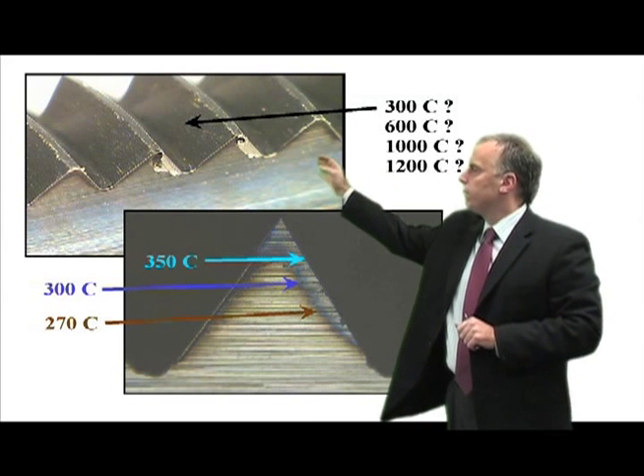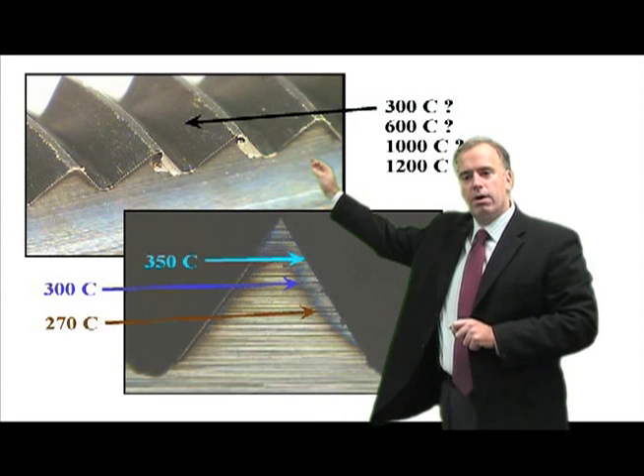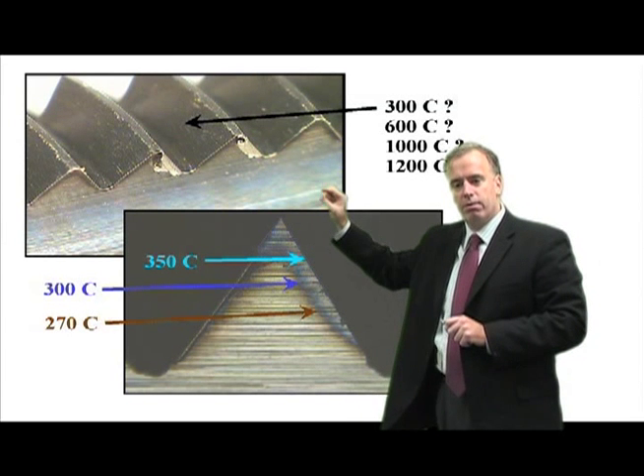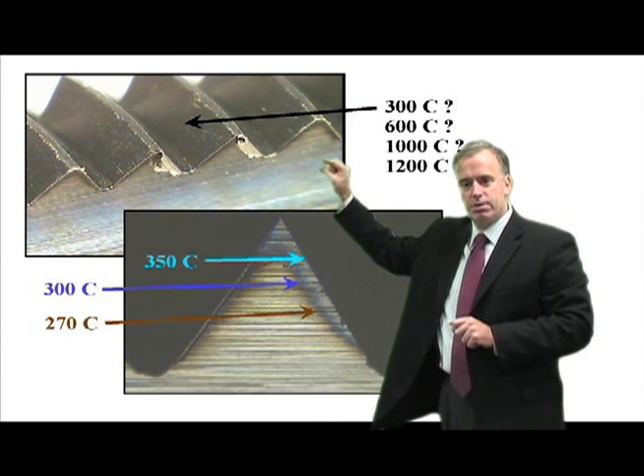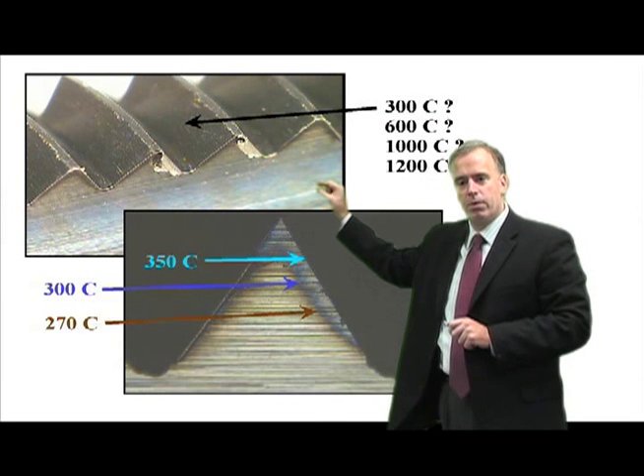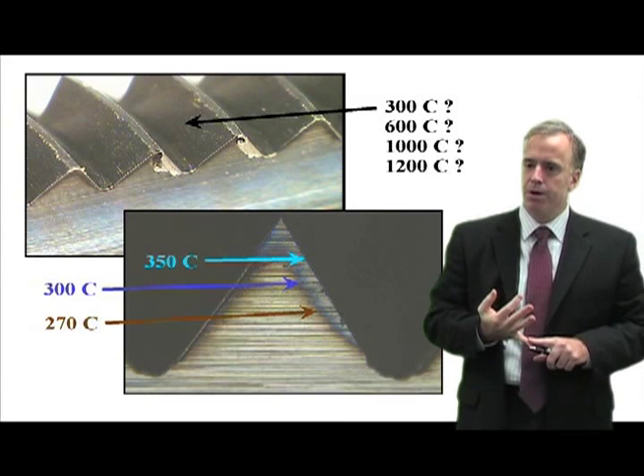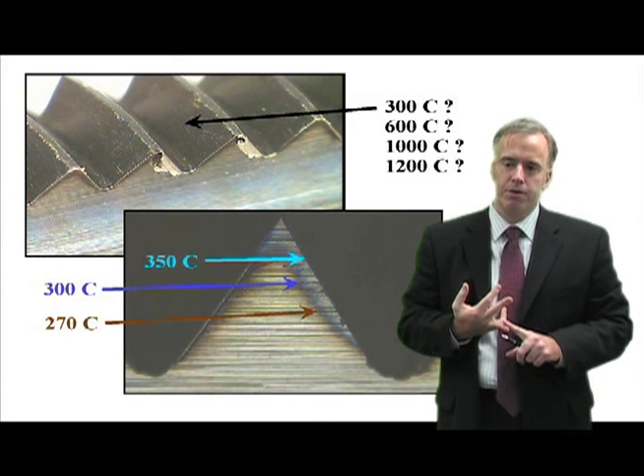Here, we don't see any oxidation burn on the ground surface from thread grinding, but we see a little bit on the unground surface in the flute area. Now, where is the part burned, or is it burned? That's extremely difficult to know.